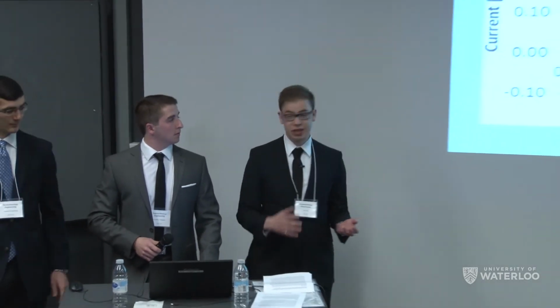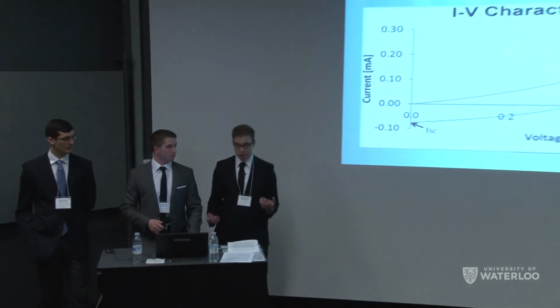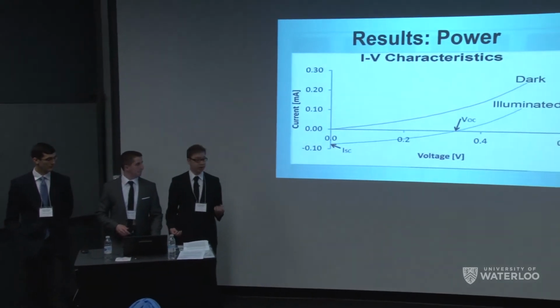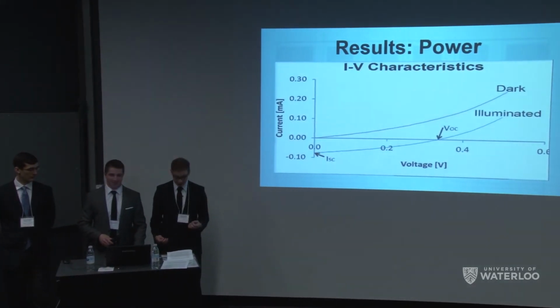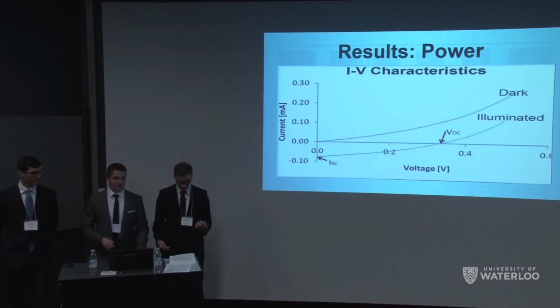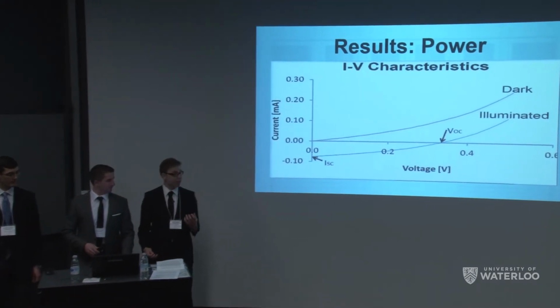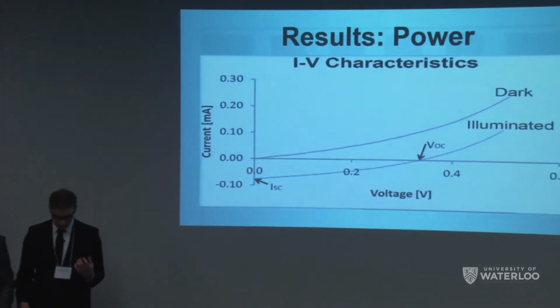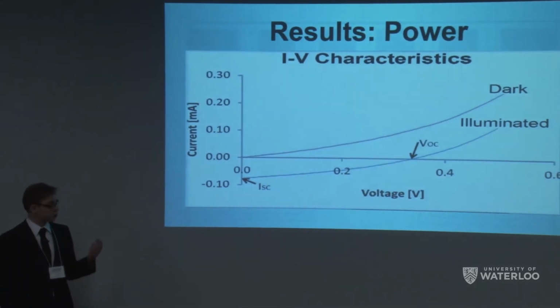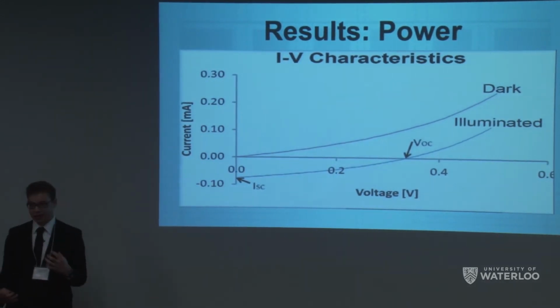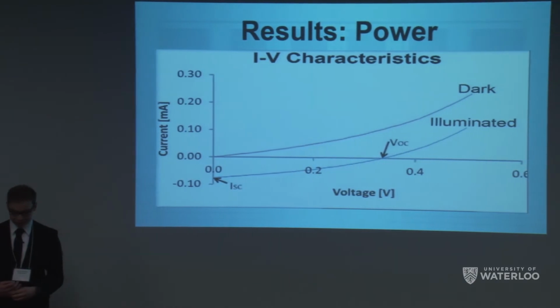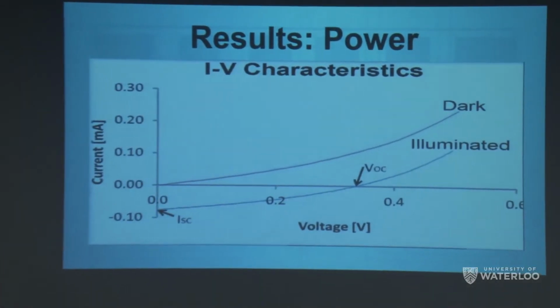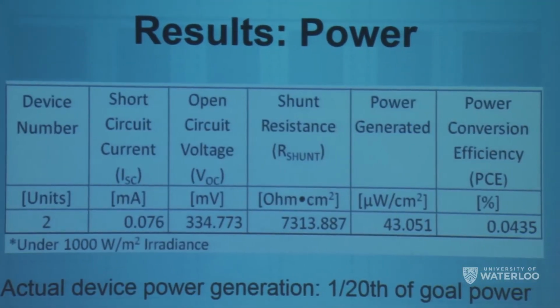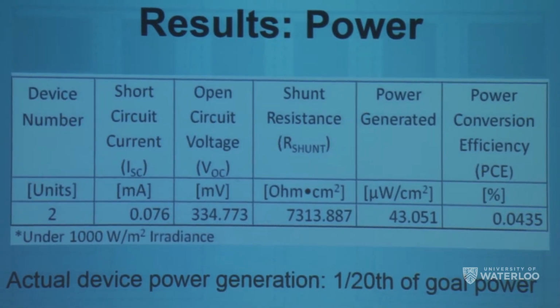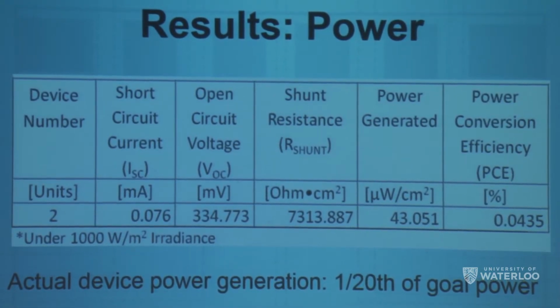We fabricated this device using our solution process active layer, and then we swapped out our silver nanowire top electrode and used a more conventionally deposited, thermally evaporated aluminum layer to validate our electrical properties. This is opaque, but it did allow us to validate these properties. The JV curve for this device actually shows a fairly shallow slope, which shows a fairly high internal resistance, which means we have some room for improvement. Also, we only generated about 1/20th of the power that we wanted, but we did prove that our active layer and solution processing method of deposition work at a proof of concept level.